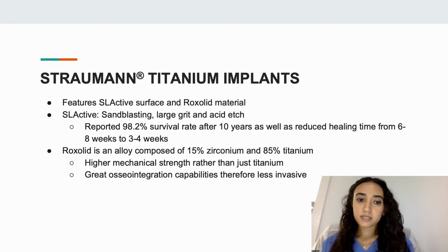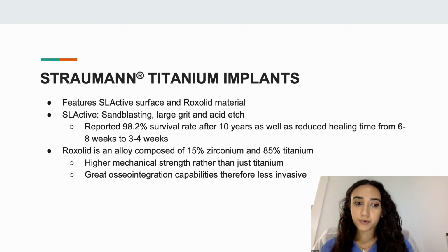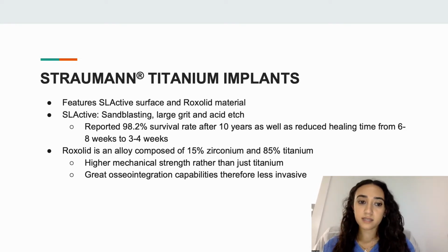The Straumann titanium implants feature two very important features. One is the SLA active surface, and the second one is the Roxolid material. The SLA active stands for sandblasting, large grit, and acid etch, and that pretty much gives the implant micropores and roughness for better cell-to-cell attachment during insertion.